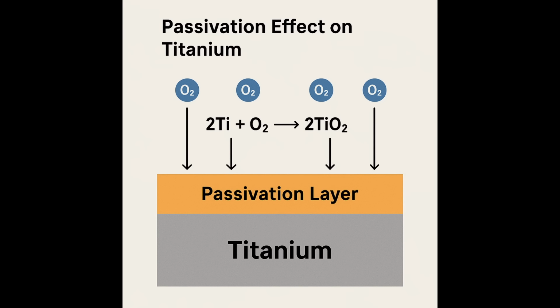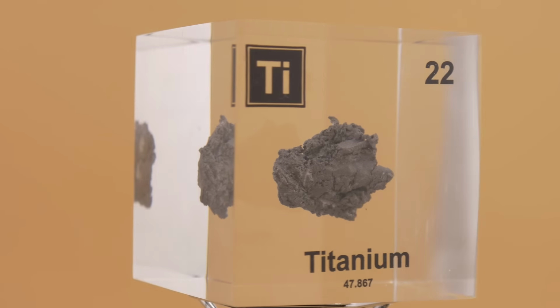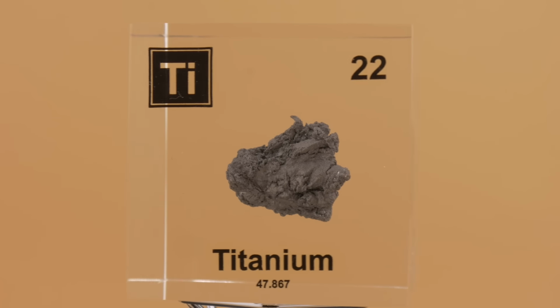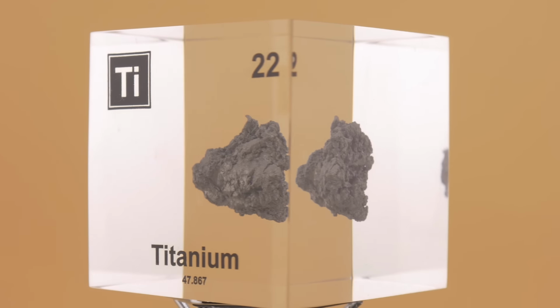But when you heat things up, titanium shows its more reactive side. In fact, titanium is a very reactive metal. We just normally don't see that because of the passivation effect. Now, if titanium is heated in the presence of air, at some point it will start to burn. Yes, you heard that right, this metal will start to burn. Titanium can catch fire in air at elevated temperatures, well below its melting point.